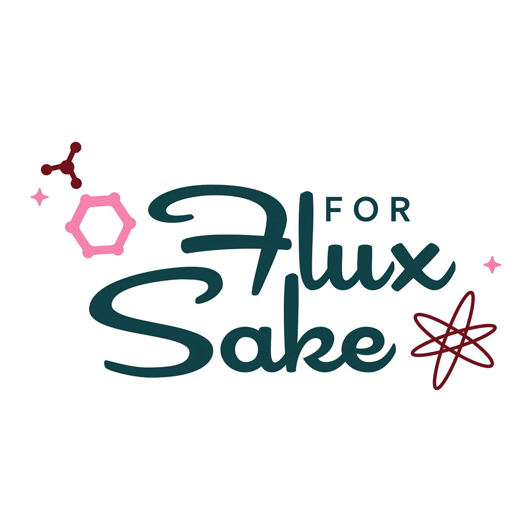And like we said, in clay bodies, it's different than in glazes. In glazes, a material goes away, you can kind of substitute anything for anything. And if you know your chemistry, it'll work. In a clay body, you don't just care about chemistry, you care about physical performance too, because it's all about particle packing and particle to particle interaction. And there is no such thing as a substitute in a clay body. There are clays that are kind of similar, but you're still going to have to tweak your recipe. But if you're in a situation where red art was, where the chemistry doesn't work and the particle packing may not work, you're really up the creek.